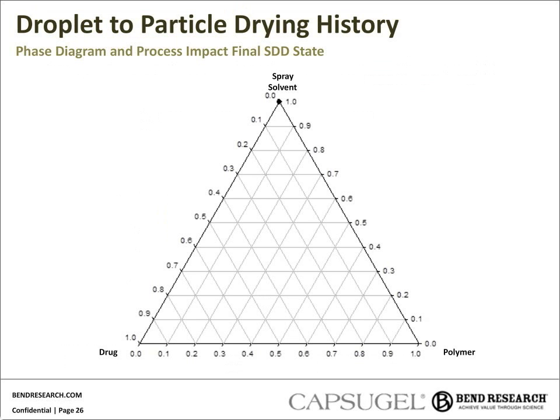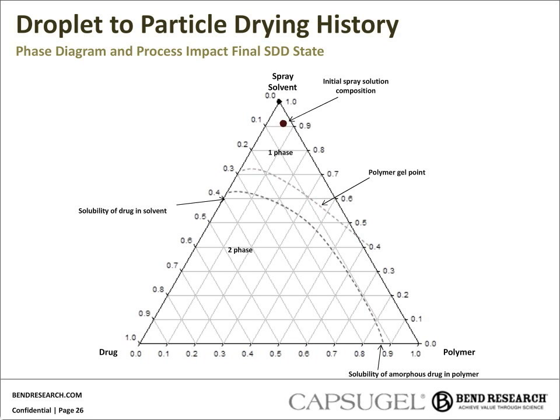Once we've crossed the bridge that we're going to be in a kinetically stabilized or metastable state, it's very important to note that we start with a homogeneous SDD, and that ties back to the process, which Dana will fill in as I wrap up my description of physical stability. Here we are looking at a ternary phase diagram where we start with an initial spray solution composition that is largely solvent. As we do the spray drying process, we remove that solvent, and compositionally we go through some very important phase boundaries. The first is the polymer gel point, and the second is the solubility of the API in the solvent that you're spraying out of. So compositionally, as we spray dry, we cross both of those boundaries.